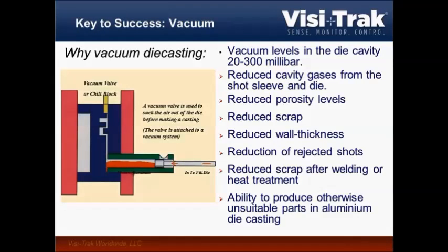Vacuum, we find vacuum die casting very often with anything between 20 and 300 millibar of remaining die pressure. It's used to reduce the cavity gases from the shot sleeve and the die, so we reduce the porosity level and therefore scrap. But very important in structural die casting, we need the vacuum to actually fill these parts with these very thin walls. Otherwise, we could simply not fill such a B-pillar or shock tower.